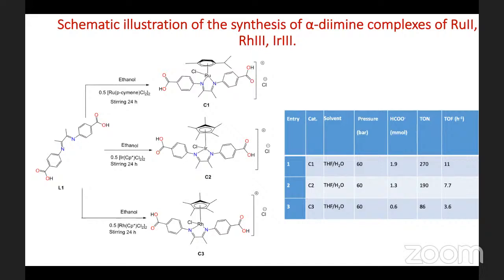What we realized is that in this table here, we have entry 1 up to 3. Under the same conditions, we realized that complex C1, which is shown here, is more active towards hydrogenation of carbon dioxide to form formate, with a turnover number of 270. And the least active was C3 with a rhodium metal center with a turnover number of 86.